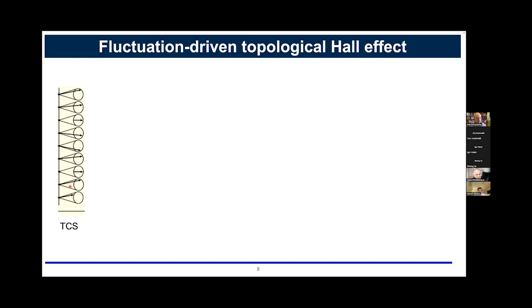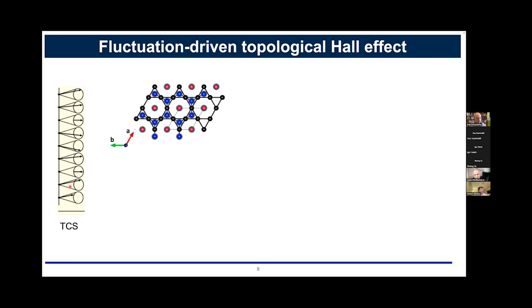What happens, and I'll tell you in a very hand-waving way, is that what plays an important role is the 2-dimensional order of these magnetic atoms. It enhances these fluctuations, Mermin-Wagner fluctuations. And because of these strong fluctuations, what happens is that this is a centrosymmetric material. We have nearly equal population of right-handed and left-handed spirals. And the fluctuation imbalances that population of the spirals, in a very cartoonish way.